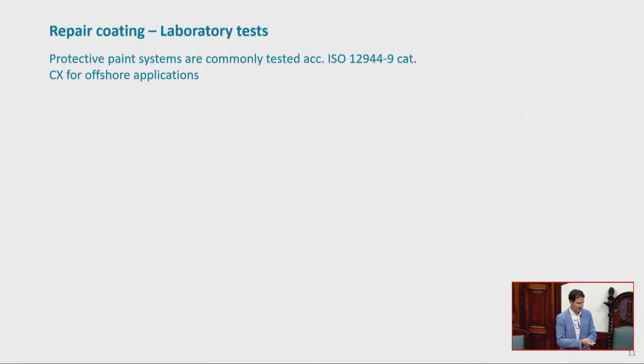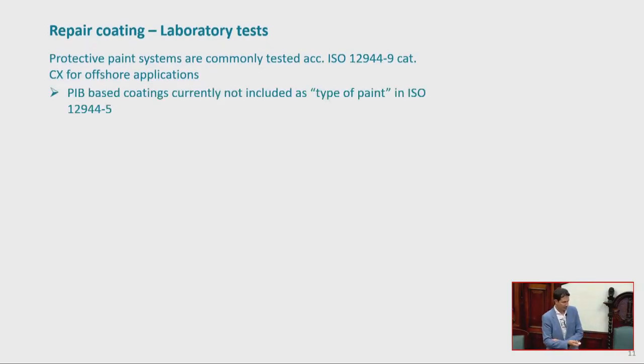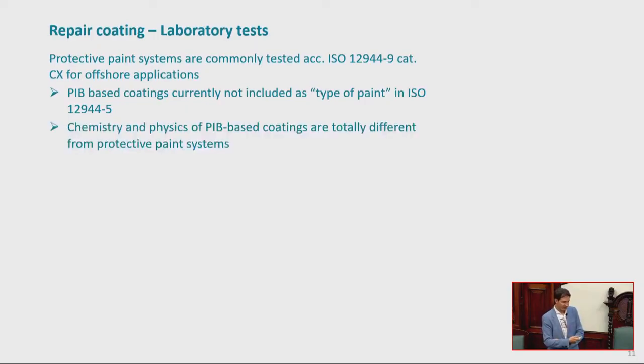I explained that. But now we needed to test it because obviously you get a lot of requirements for testing. And we tested according to 12944 CX conditions for the offshore. That standard is not made for these kinds of coatings. It doesn't specify them anywhere. It's 3-layer coatings. So how do you create a coating that will accommodate to these things? So I'll just run you through it. Some things are great, some things are not good. But I will show you failures. So in a way, I'm also questioning this standard. And I'll show you reasons why this standard is also being questioned.